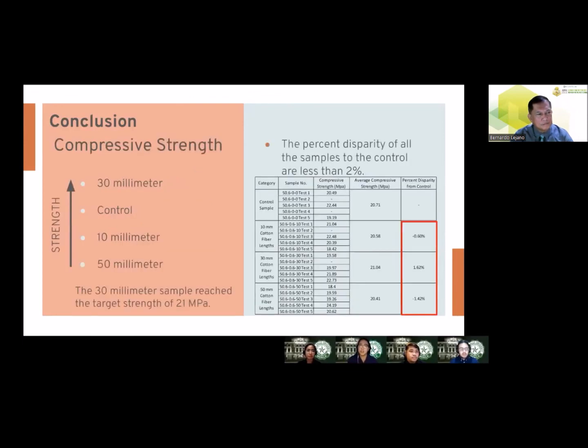The results of the compressive test showed that the 30 mm concrete samples had the highest strength out of all the other specimens. The control specimens had higher strength than the 10 mm samples and the 50 mm samples. However, the strength did not vary widely, seeing that the percent disparity of all the samples to the control is less than 2%. Therefore, the addition of fibers and varying length of fibers do not significantly affect the compressive strength of concrete.